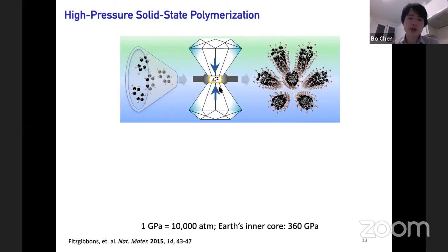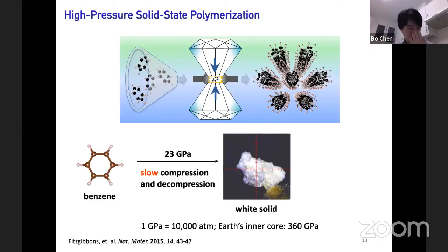So in order to achieve such high pressure, the sample size really has to be small. And usually the sample size is on the scale of micrograms, it's really tiny. But in this case, we don't really need such high pressure. We only need around 20 GPa. So when benzene is slowly compressed to 23 GPa and slowly brought back to ambient pressure, a white solid is recovered.